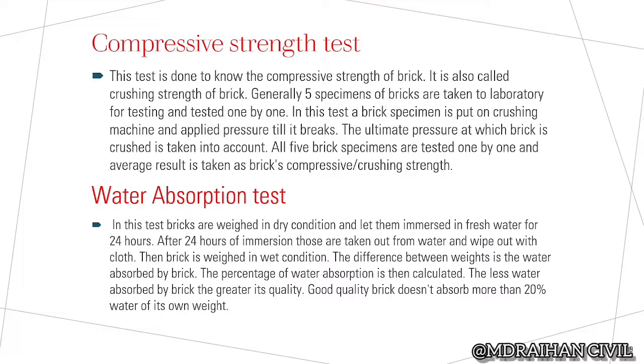Water absorption test. In this test, bricks are weighed in dry condition and immersed in fresh water for 24 hours. After 24 hours of immersion, they are taken out of the water and wiped with a cloth.